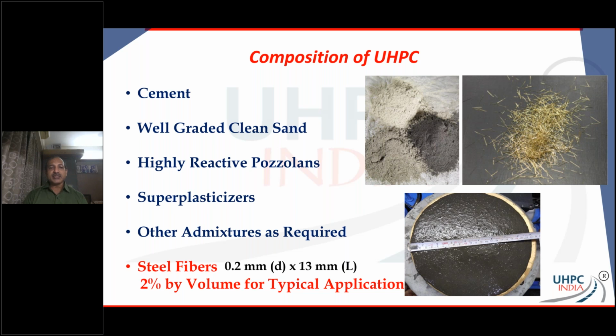But remember, the size is very important. Let's not come in and say that I can add 0.4 mm steel fibers or 0.35 mm steel fibers, because even if you add those 2% out there, you're going to reduce the number of steel fibers, and that's a problem. Because if you reduce the number of steel fibers, the nice composite behavior of the UHPC changes, right? So you want as high as you can the number of steel fibers in the mix. Even if you can find 0.18 mm diameter steel fibers, go ahead and use them, because it's going to make the behavior a lot better.